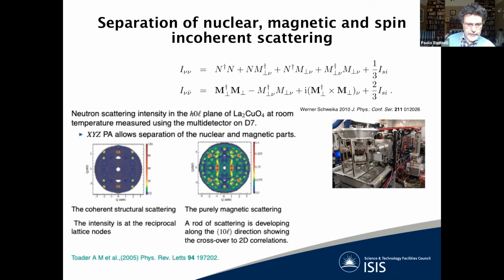So this slide illustrates how you can separate the magnetic diffuse scattering here on the right from the coherent structural scattering here on the left, and the experiment is from D7, classic experiments done on this instrument, and they rely on measuring separately the intensity of non-spin flip here on the top and spin flip here on the bottom in different directions. And to do that, you need a device that guides the polarized neutrons with a particular orientation of the samples and then guides them back to the detector.